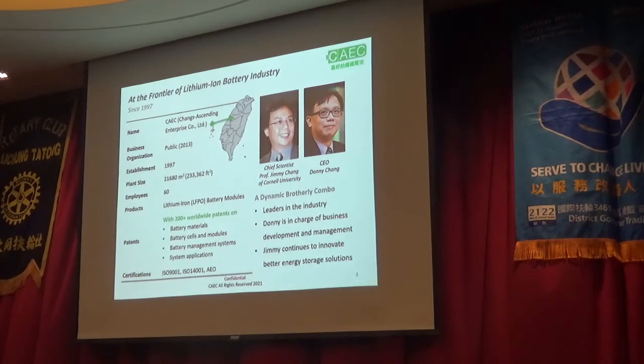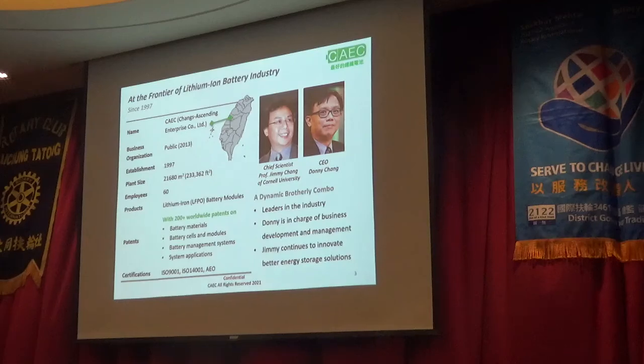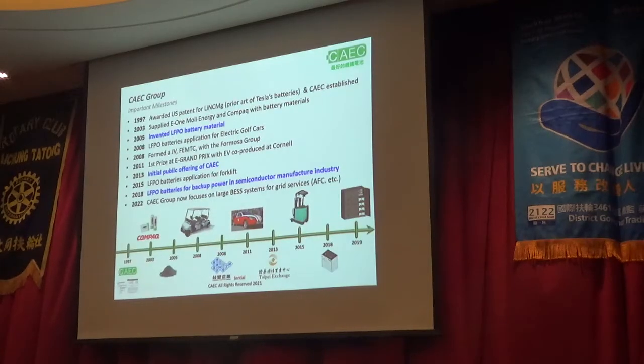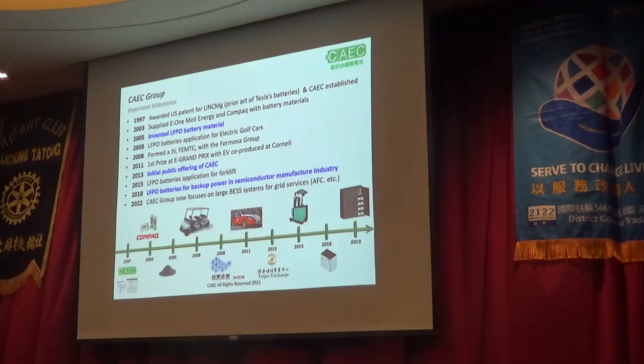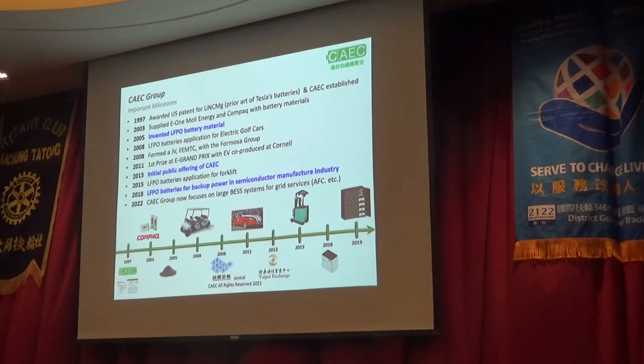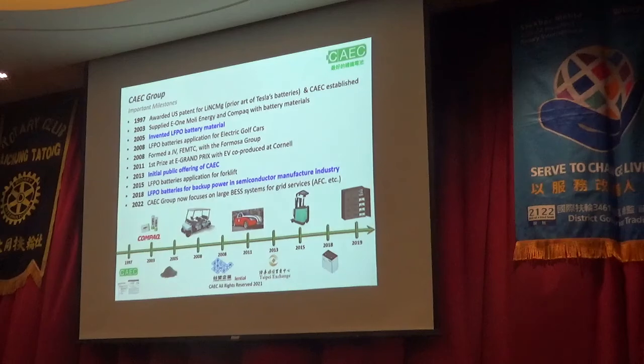So, and then the company had its IPO back in 2013, after how many years? 16 years of hard working, let's say. Okay, so started in 1997, in 2005, we had a big change of the materials being fabricated. So we call it LFPO, it's lithium iron phosphorus oxide. This material is intrinsically different in structure from the layer structure materials as I just mentioned, the materials being used by Tesla. And since then, it's a safer material because the material itself is more stable.